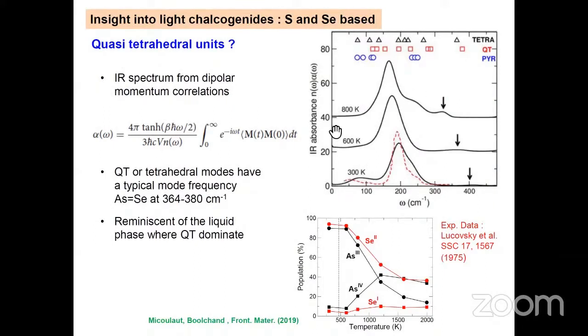Here's an example for As2Se3, where you can see that at ambient, you reproduce the main features of the experimental spectra, which you see as the red broken line. And furthermore, I should mention that this infrared spectrum is calculated from the Fourier transform of the polarization autocorrelation function.